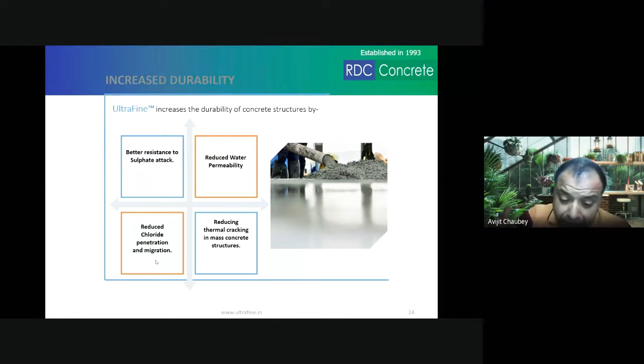One government body in Mumbai has now actually migrated from the rapid chloride penetration test, RCPT test, to the RCMT test, rapid chloride migration test. The reason being, RCPT was a kind of wrong test because it was also measuring the current that flows through concrete. So, for example, you have a concrete in this RCPT test assembly, and you are passing the current through the solutions of sodium hydroxide and sodium chloride. Now, the assumption was that when the chlorides move across the concrete, the current flow will be higher.